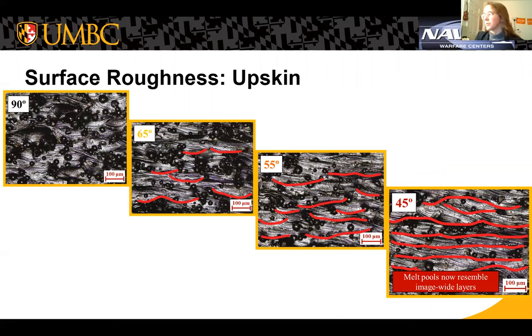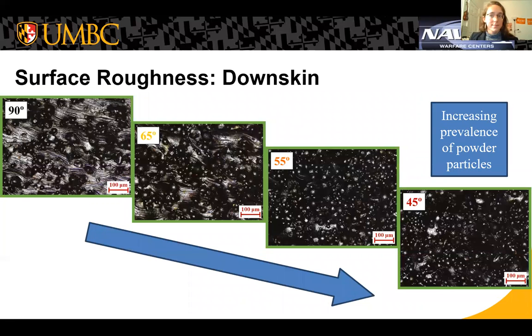We were able to get these really great images, and essentially what has happened is as the angle decreases, we see more and more of these image-wide layers and the elongation of the melt pools. We also see fewer clusters of powder. And it's the opposite on the downskin surfaces. We have an increasing prevalence of powder particles and a decrease in the visualization of those flowing melt pools.